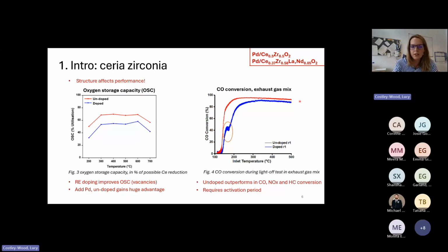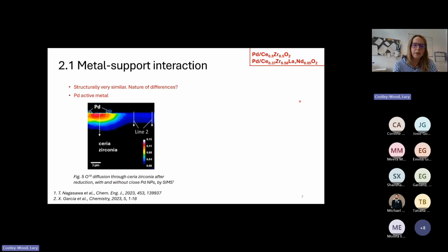And we know that this interaction is really important because, for example, here is a study that was done by Nagasawa in 2023. This shows an image where this is a ceria zirconia and these are palladium nanoparticles. And they reduced the structure and then they exposed it to labeled oxygen, so oxygen-18. And this shows the concentration of the oxygen-18 and the diffusion of it into the ceria zirconia in an area that's surrounding palladium nanoparticles compared to an area that isn't. And you can see how being in proximity to palladium improves the oxygen diffusion.